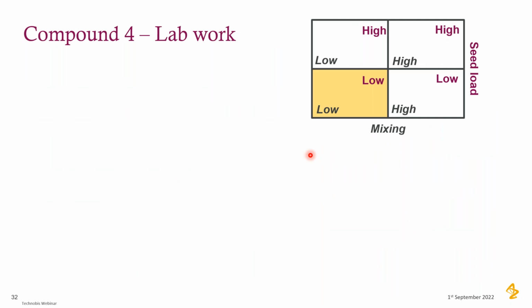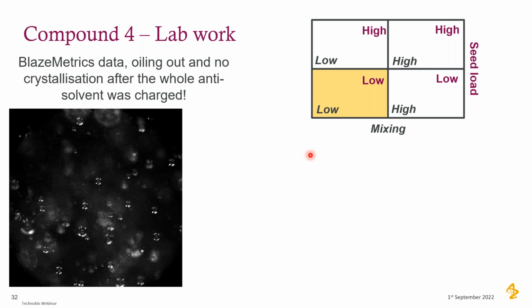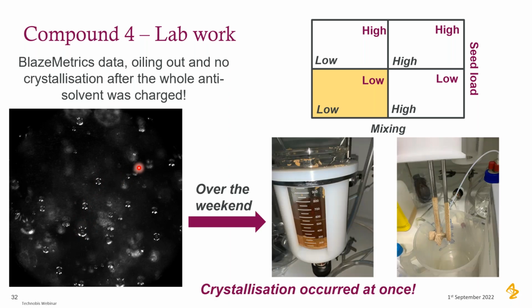So when we started experiment 1, which was basically the worst case scenario, low seed loading and low mixing, we saw, using BlazeMetrics, which is basically a probe we put in the reactor, lovely bubbles. So actually that's an oiling out. And then later on, at the end of the process, we still saw those lovely bubbles. And then over the weekend, those lovely bubbles crashed out, and you can see the material at the bottom of the reactor, basically covering completely any kind of baffle present in the batch. So the crystallization was very rapid, and when we looked at the form of that solid, it was basically a mixture form. So we observed an oil and a mixture form and no control of crystallization for low mixing and low seed loading.